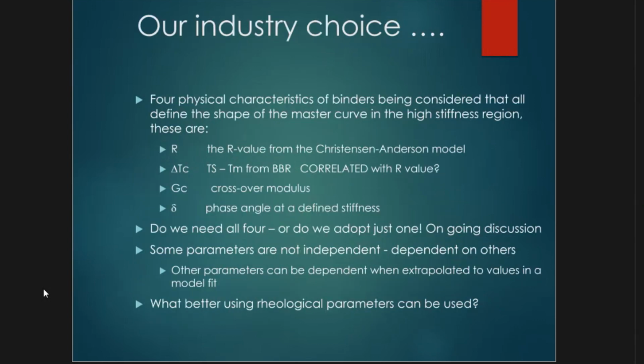The four physical things I like to talk about here, first, they're thinking about whether we could have one thing that tells us, at least from the binder point of view, that we could say, hey, this is the number. We have some numbers for the R value that came out of Christensen and Anderson. It's a rheological model, and if you are within 2.5, it has to do with the cracking at low temperature and aging.